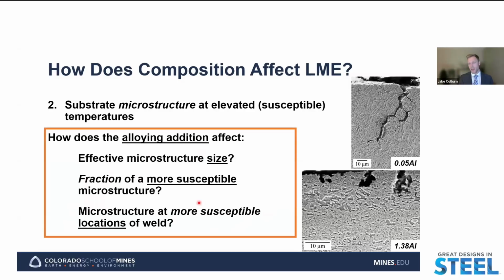So whether we have an intercritical or supercritical HAZ in an AHSS, or potentially some other type of heat affected zone or microstructure at those susceptible locations of the weld, is important. So we would be interested in knowing how that aluminum addition is going to affect, for a given weld parameter, what the microstructure would be at the weld shoulder and weld periphery.